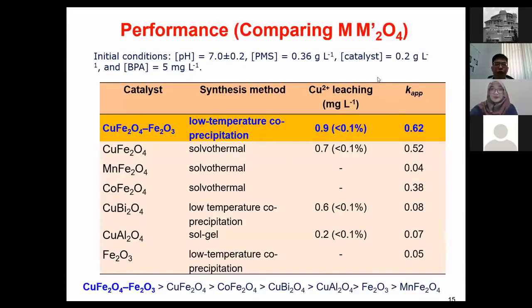So to show you some of our results, this one we prepared with a low temperature co-precipitation method, and then we compared with different types of catalysts prepared using different methods. For example, copper ferrite prepared with the solvothermal method, copper ferrite also solvothermal methods, and so on. And we found that, of course, our catalyst prepared by the low temperature method gave the best rate constant. This is the pseudo first order rate constant, and it is the highest if you compare with other different types of mixed metal oxide, and also this single metal oxide.